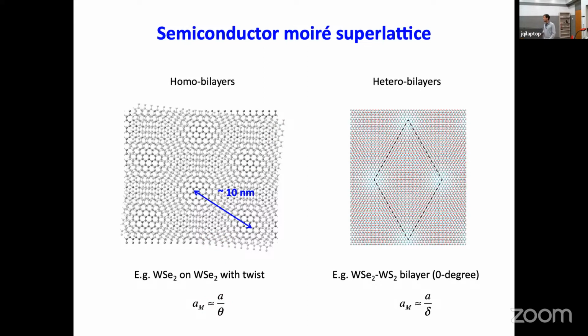Another way to make a Moiré heterostructure, which is somewhat different from graphene, is that now you can choose two different materials and make use of the lattice mismatch between them. For instance, I'm showing an example here of tungsten selenide on top of tungsten sulfide, and there's a 4% lattice mismatch between the two materials. So even if you put them at 0 twist angle, because of the lattice mismatch, you also get a Moiré superlattice structure with period on the order of about 10 nanometers.